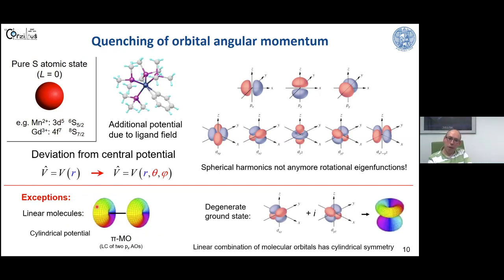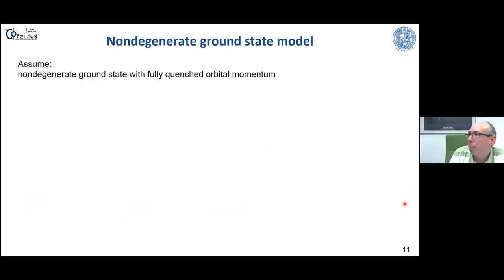and we also can have angular momentum inside a ligand field if we have a degenerate ground state, for example, in such a case where we have degeneracy between the dxz orbital and the dyz orbital. If we linearly combine them, we reverse the way we generated these two real orbitals, and we arrive again at a complex orbital which has full rotational symmetry around the z-axis. So in such a case, if we have one electron situated in a degenerate set of these two orbitals, we have full orbital momentum again. Okay, but let's not talk about these exceptions, because we want to arrive at a state where we have no orbital momentum.